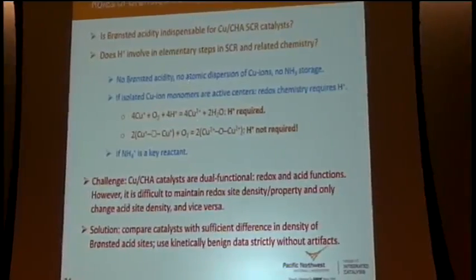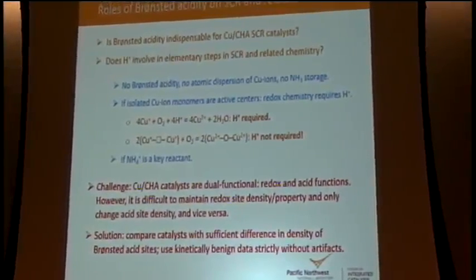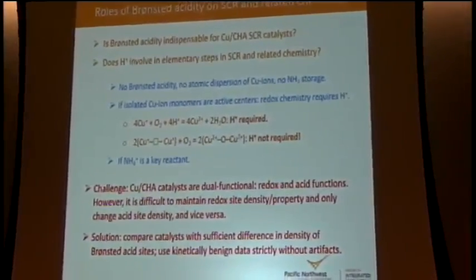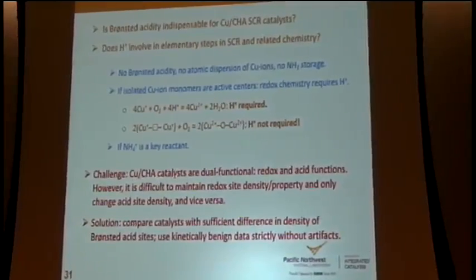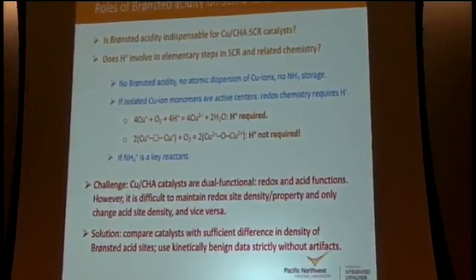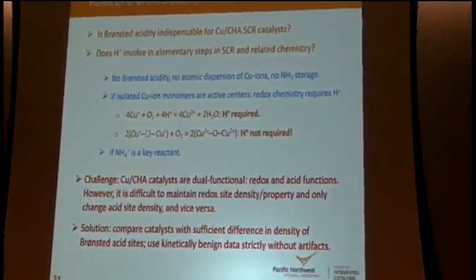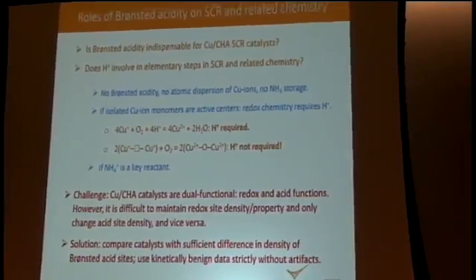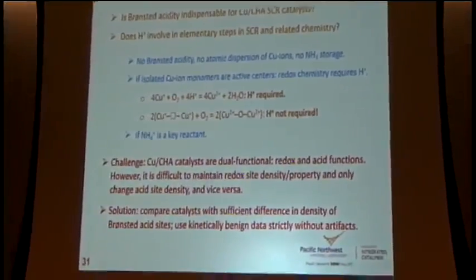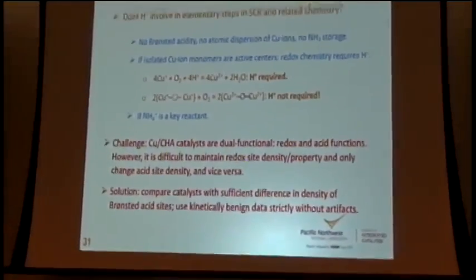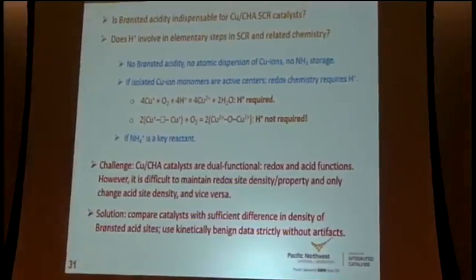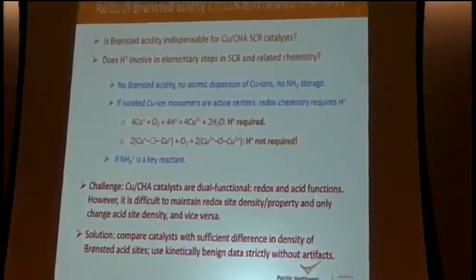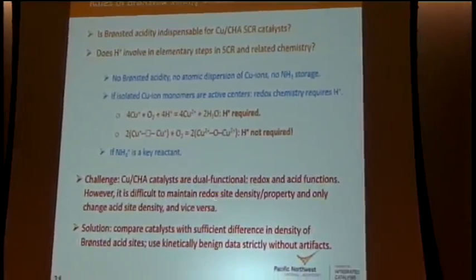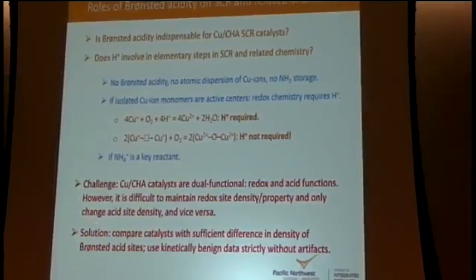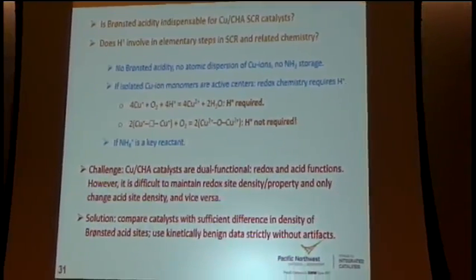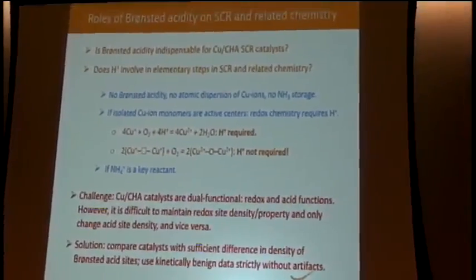To study the effects of Brønsted acidity, there is a challenge, which is that the copper chabazite catalysts are dual functional. They provide both redox and acid functions. As properly trained researchers, if we want to study effect A from effect B, we want to keep only one parameter changing, the other fixed. However, in this case, it is difficult to maintain redox site density and property and only change acid site density. And the same situation is true in other cases.